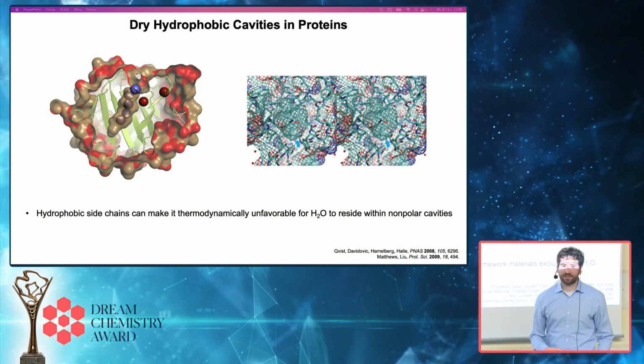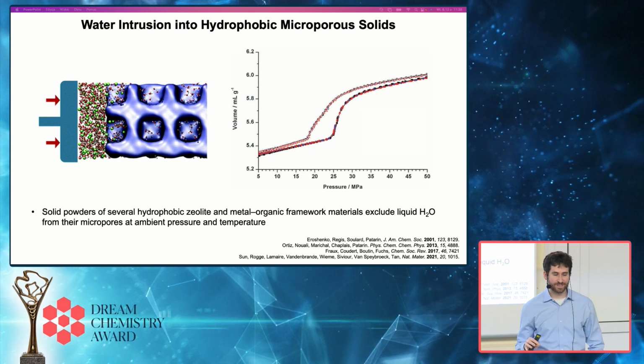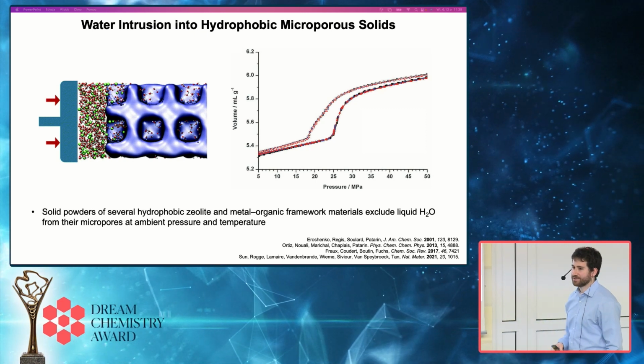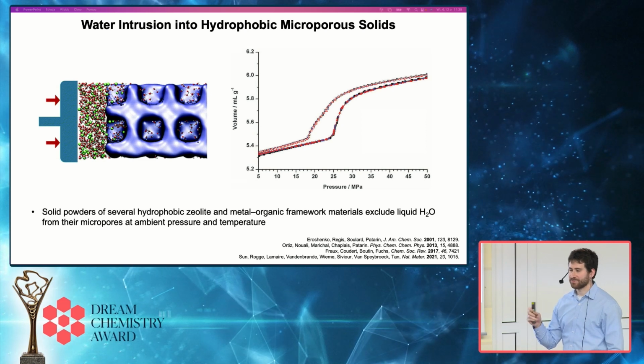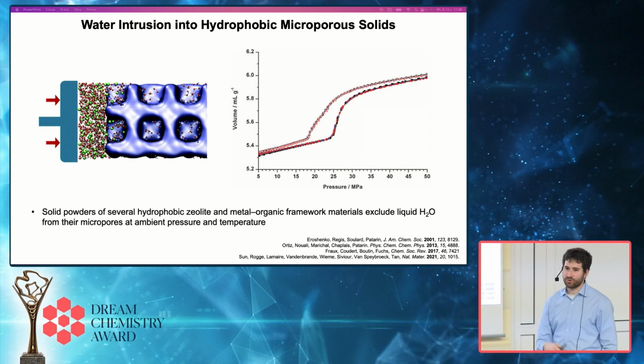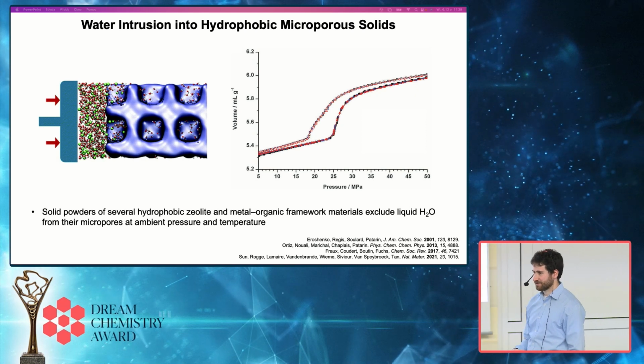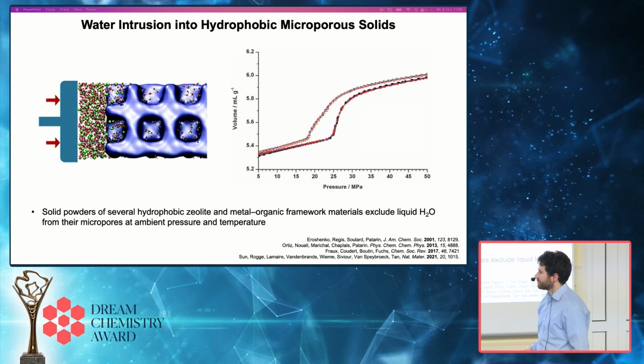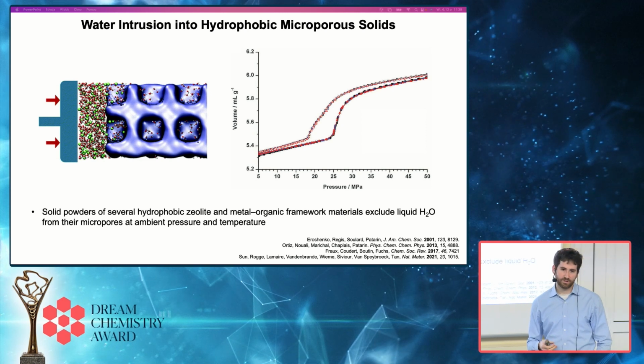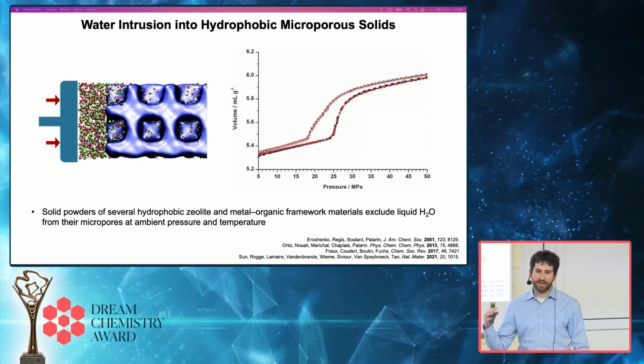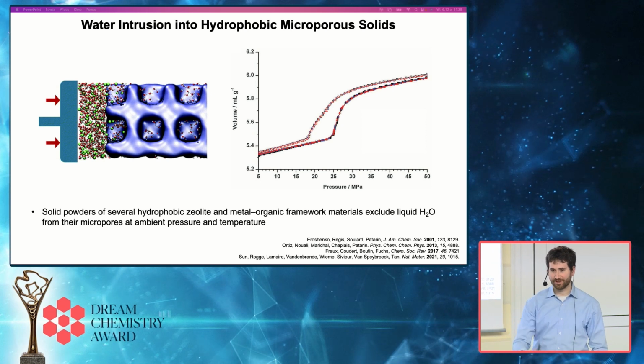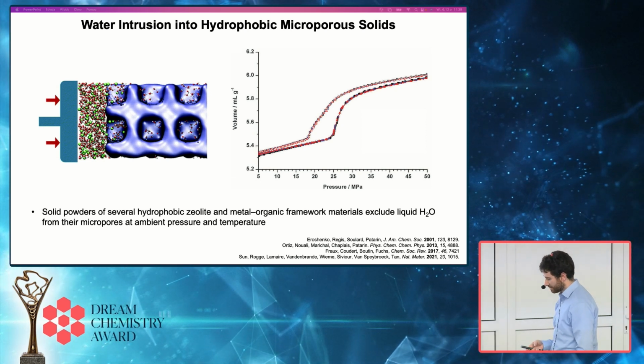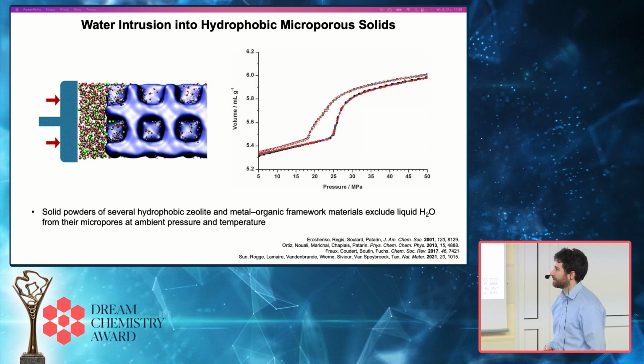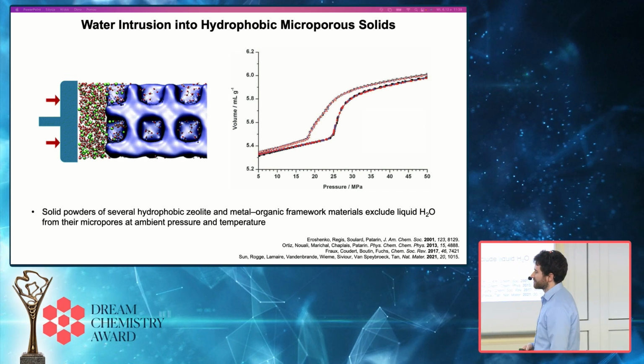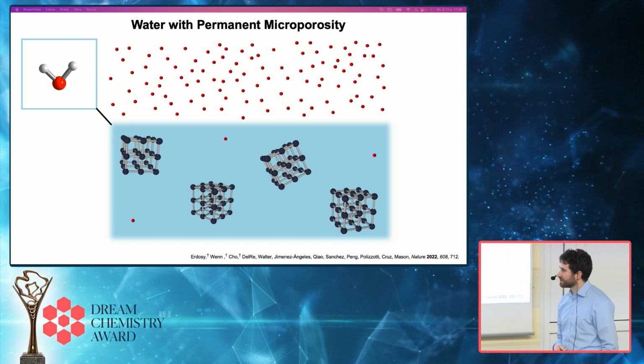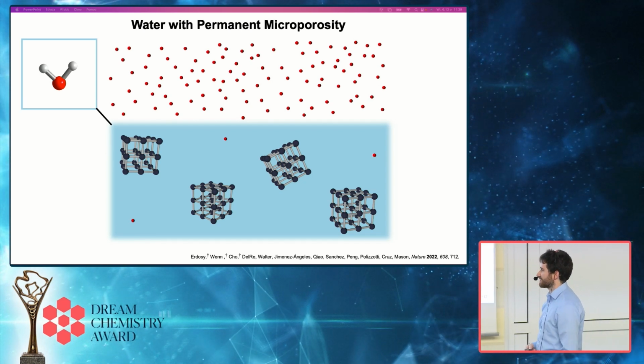It's also known that if you take hydrophobic porous materials, think like activated carbon, and you put them in contact with bulk water, it can often require significant amounts of pressure in order to force the liquid water into the pores of that material. So for activated carbons and for some really hydrophobic zeolites, it's known that you have to put anywhere from 200 to 800 bar of pressure in order to force water inside the pores of a hydrophobic solid. And so this made us think that there was kind of a thermodynamic approach that might work for preserving porosity of microporous materials in water and preserving their gas accessibility.